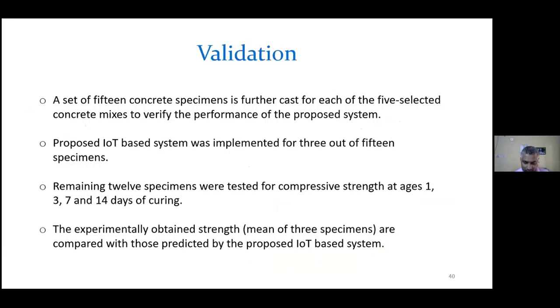Now to validate this, a set of 15 concrete specimens was further cast for each of the 5 selected concrete mixes. So 5 into 15, 75 specimens we have mixed, 15 for each of the mixes. Now the proposed IoT-based system was implemented for 3 out of the 15 specimens, and the remaining 12 specimens were tested for compressive strength at ages 1, 3, 7, and 14 days of curing. The experimentally obtained strength, the mean of 3 specimens, is compared with those predicted.